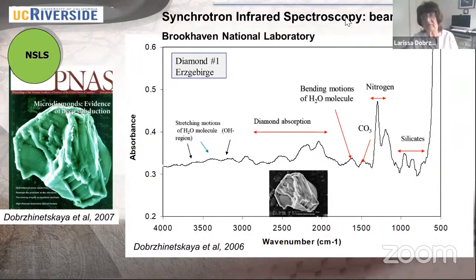So let's see here this synchrotron infrared spectroscopy. This graph shows the wavenumber in centimeter^-1, and this is absorbance. What we recognize here is that this diamond contains the stretching motion of the H2O molecule. It's the OH region, all these small peaks. Then these are diamond absorption peaks. Then we found this specific peak at about 1,630 centimeter^-1, which is a bending motion of the H2O molecule. It means there is molecular water there. Then we found the CO3 radical, some carbonate. Then we found nitrogen, and nitrogen has two peaks, a big and a small peak, and also two peaks at this distance. They show that there are silicate inclusions inside of this diamond.